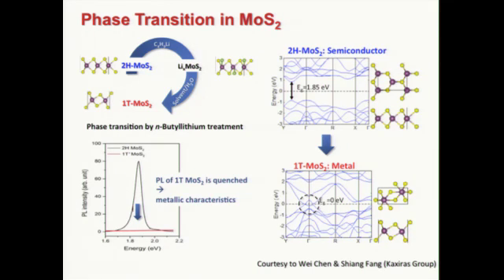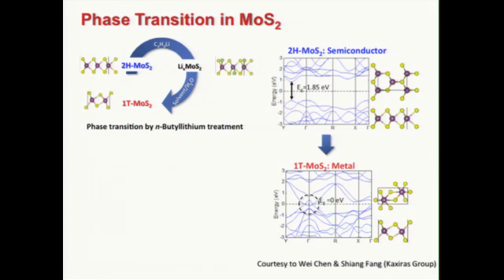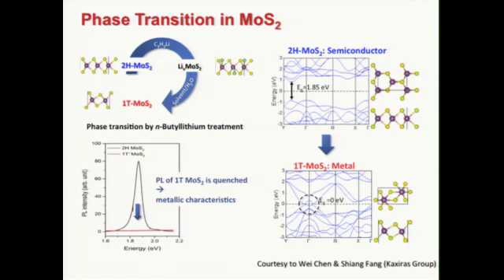You see here PL before and after. Single layer molybdenum disulfide is a direct bandgap semiconductor, so it has a very sharp PL peak. After the phase transition, as you see, the PL is 100% quenched. So that's because the bandgap is closed, and that's what you see also here in this DFT calculation done by my colleagues. So the metallic one, the gap is completely closed.